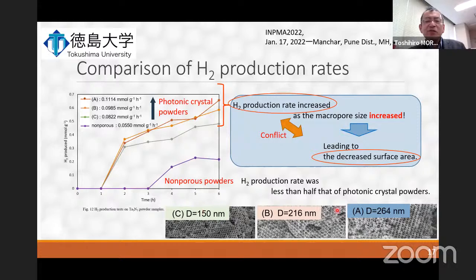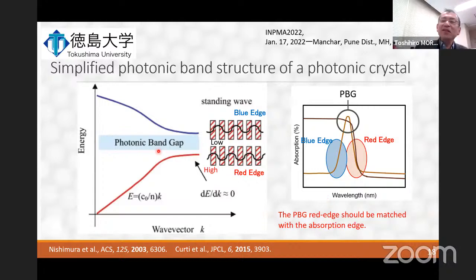Increased pore size will usually lead to decreased surface area. That means degradation of photocatalytic activity. Usually larger pore size gives poorer photocatalytic activity, but in our result, it is inverse. Increased hydrogen production with increased pore size, which results in decreased surface area, conflict with each other usually. But we think like this.